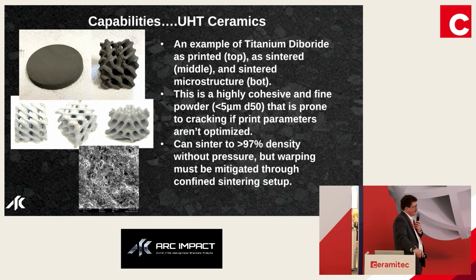So in this case, what the partner company was looking at was titanium diboride. It was actually a titanium diboride nickel system where they were having a very tough time producing unique geometries in any other way. So we said, okay, give us some powder, we'll print, we'll see what we can do. Went through a couple iterations of that printing and that post-processing, and they were able to get greater than 97% density on some parts. Some more tuning, they were able to do so without great deformation. This was sort of an early iteration where they were getting some deformation in the z-axis, but with proper containment and proper sintering setup, they were able to minimize that distortion.